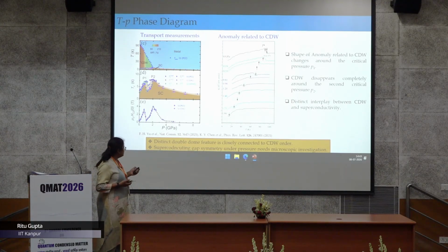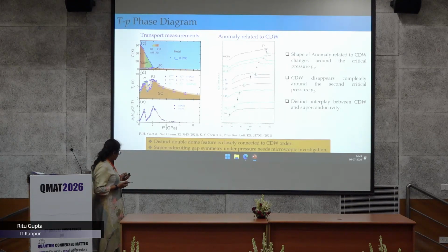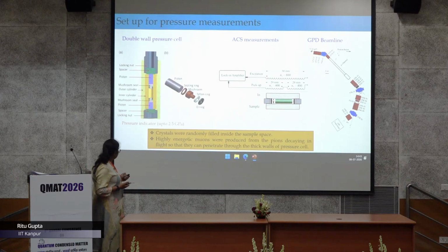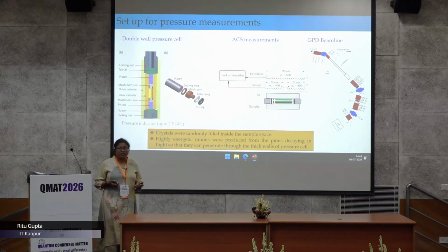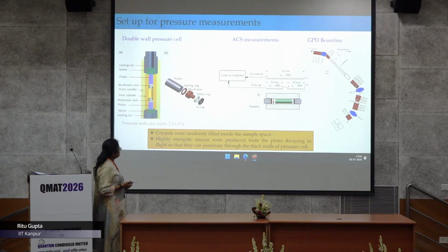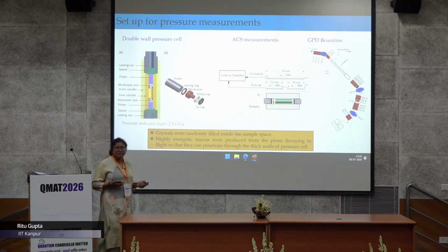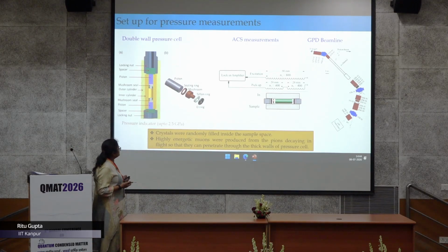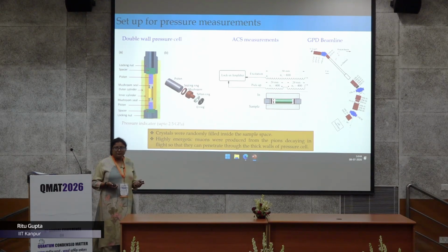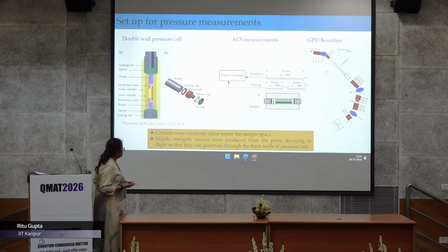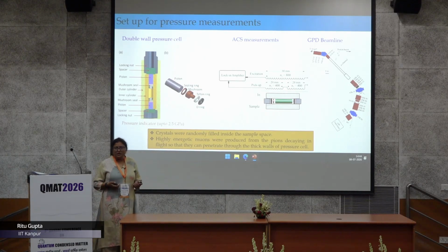So that is why we carried out the experiments under pressure, and this is the pressure cell which was being used. I will not go into much detail, and we can reach up to pressure 2.5 GPa at low temperature. And before going for the actual experiment at the beamline, we do AC susceptibility measurement. We put one pressure indicator along with the sample, and we determine its Tc at low temperature, and that's how we calibrate the pressure.